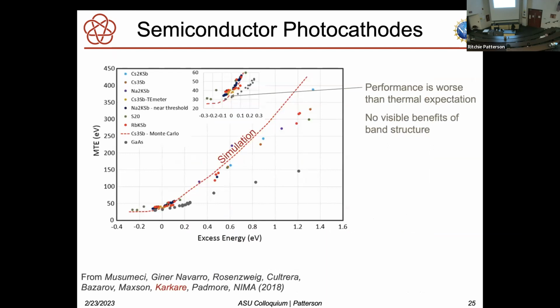Here is some data compiled for a lot of these different photocathodes. And you can see, again, this is the excess energy of the photon versus the mean transverse energy. One thing you can see, if you zoom in on this region down here, is that you never really get to quite what you think you ought to. You never achieve thermal MTE, even with very low excess energy. And that's not entirely understood.